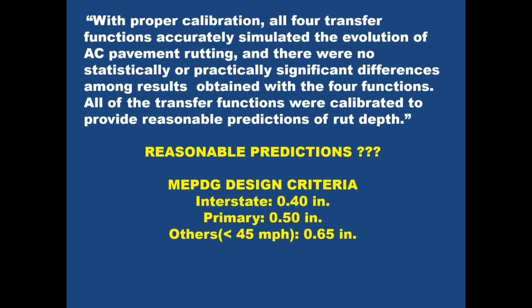So what's a reasonable prediction for a rut depth? If you're looking at a design of an interstate, failure is about 4/10 of an inch, primary route, 1/2 an inch, others, local roads and streets, maybe 6/10. These are values picked out of the MEPDG design criteria.